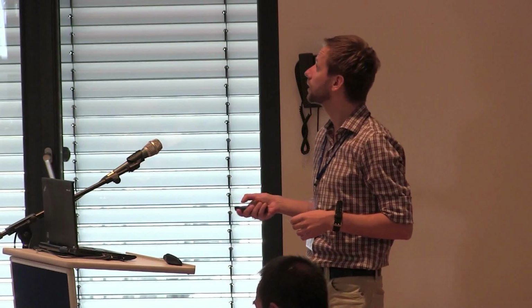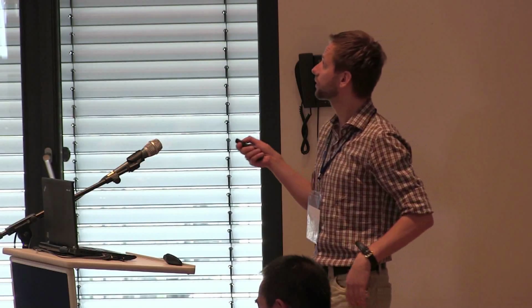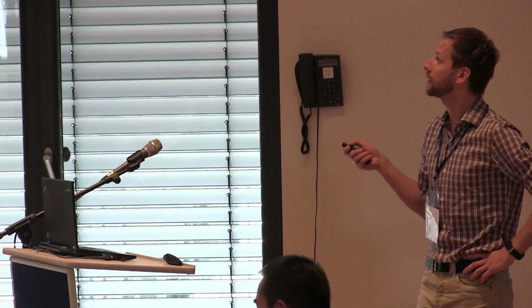Then, of course, graphene is very compact, only one layer thick. And it also has a field effect, so you can control the conductivity by changing the potential on graphene. So it all looks super perfect for ultra-high-speed electronics, and indeed people started making transistors out of it. Of course, you cannot make a logic transistor that you need to close, because graphene has no band gap, so you cannot move the Fermi edge into the band gap. But you can make a high-frequency amplifier, the HEMT-type transistor.